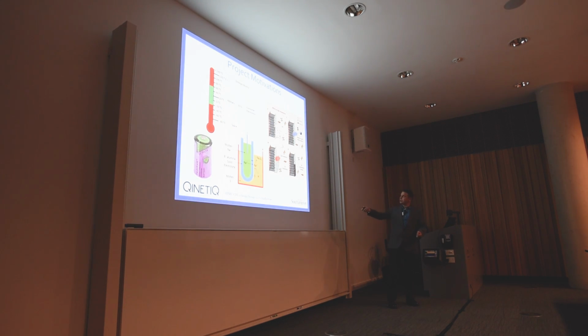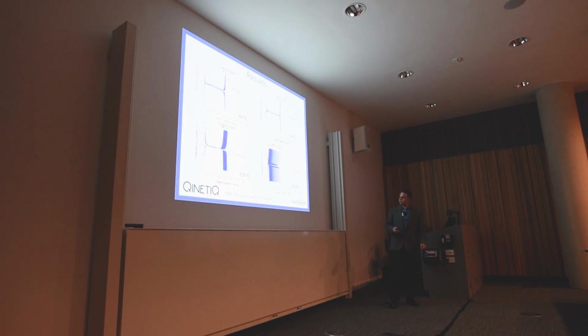However, this is quite a challenge due to the instability of the electrolyte interface. So far my project has looked at changing the binders and then went on to looking at electrolytes. So these were carbonate-based electrolytes with alternative lithium salts in them, and I've tested these at a range of temperatures going from 60 degrees up to 150.